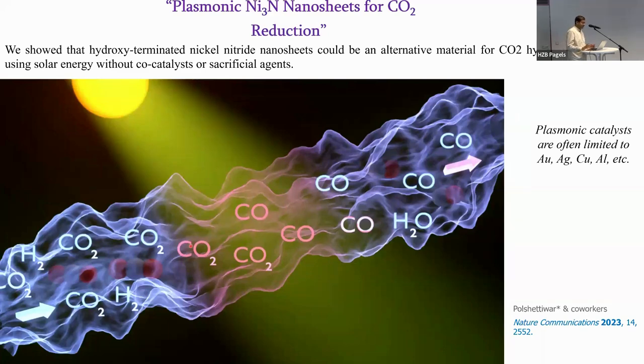Another question that we ask is, most of the time, if you see literature, whenever you see plasmonic, it's all about the metal nanoparticles. But the metal nanoparticle doesn't really have a reactive surface, right? It doesn't have OH, doesn't have amine, so it doesn't really allow you to interact with lots of chemicals, lots of reactants. So we ask this question, can I make something which is still plasmonic, but has some sites on the surface? And that's where we synthesized these nickel nitride nanosheets. And these are really thin layered nanosheets of nickel nitride, which has an OH termination on the surface. And this OH acts as some sort of a base, interacts with CO2, concentrates the CO2 onto the nickel nitride, and then you expose it to the light and you carry out a CO2 reduction reaction. It already has nickel, so you don't need to put another nickel in this one. So this was another work where we showed that one can replace the metal nanoparticles by the nitrides, metal nitrides.